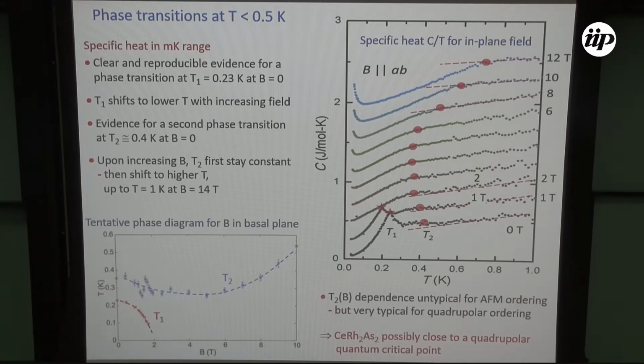So this leads to this tentative phase diagram for B in the basal plane, and this increases until 1 Kelvin at 14 Tesla. That is very untypical for antiferromagnetic ordering, but is quite typical for quadrupolar ordering. And this is an indication that we might have, in CeRh2As2, we might be close to a quadrupolar quantum critical point.